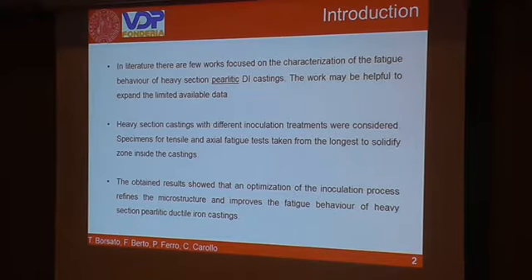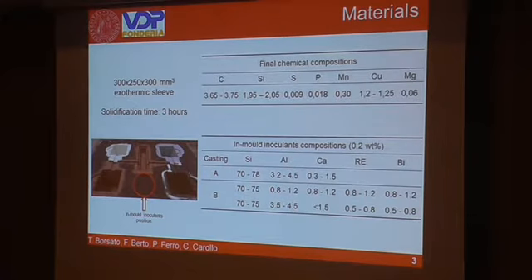The obtained results showed that an optimization of the inoculation treatment optimized the microstructure and the fatigue behavior of heavy section pearlitic ductile iron castings.